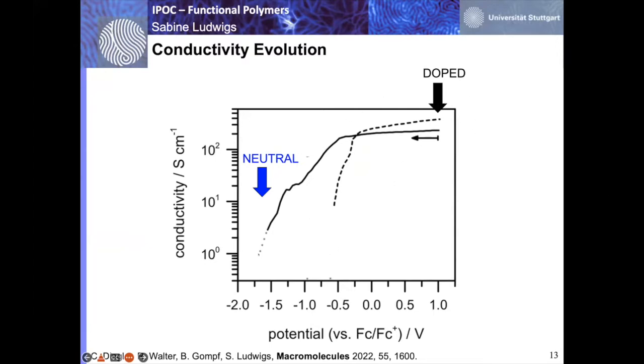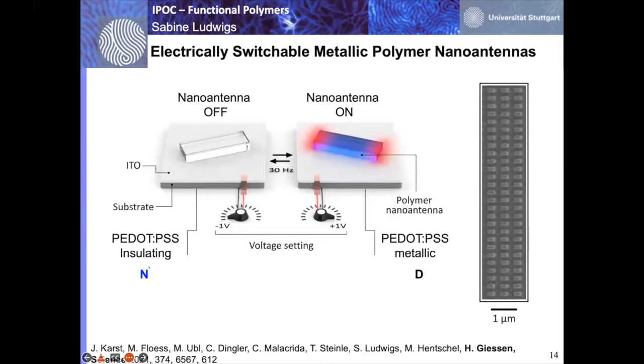And at low potentials, we come to the neutral state, so when there's no real conductivity measurable. So here we can also talk about a metal-like state in the doped state, and a neutral, non-conducting, insulating state at low potentials. And this is what we are making use of together with my colleague, Professor Giessen, who is an optics and photonics